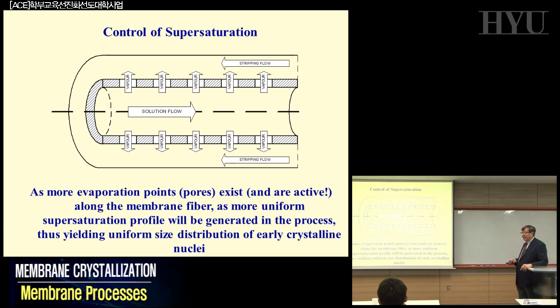But what is more important is that in normal crystallizers, having a highly homogeneous crystal formation is not so easy, because you have a big pot and the evaporation is not easy to control where it happens. You can have an area where there is stagnation, you have to have big mixing, etc. In membranes, in principle, if what we are saying is true, each pore is a place where crystallization takes place, where a certain level of concentration can be reached. So you can have a quite homogeneous distribution of the crystals that you are going to form. So it's much easier and much more controlled to have a kind of homogeneous system.